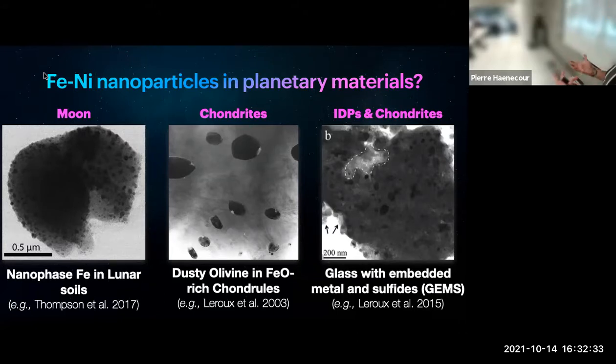Space weathering is a typical way of producing those iron nickel nanoparticles, which is similar to what we have seen, for example, with the flash heating. So it's consistent with what you would expect for an impact, a really quick high temperature event. Or you can imagine a cosmic ray particle basically bombarding the sample, hitting it quickly, forming those particles. So it's similar to what we have seen with the first experiment of nanophase iron.